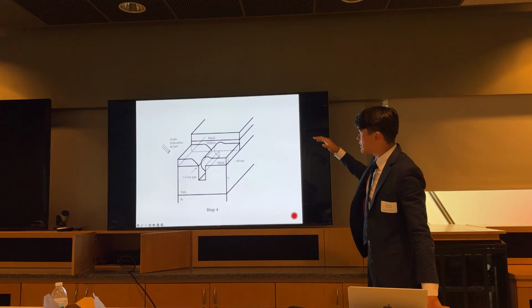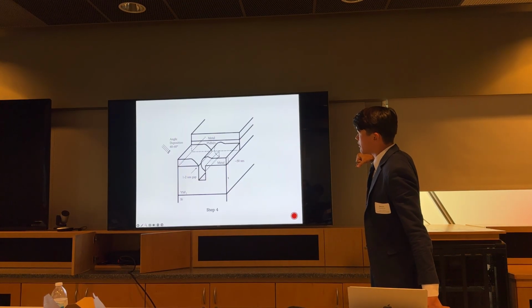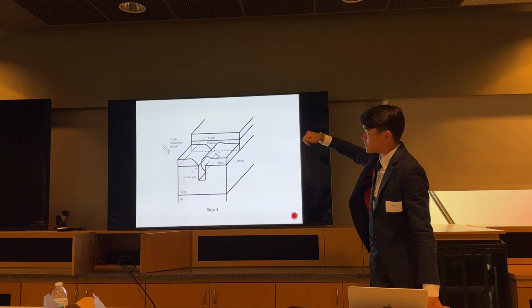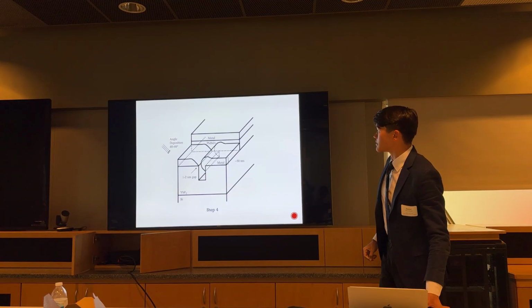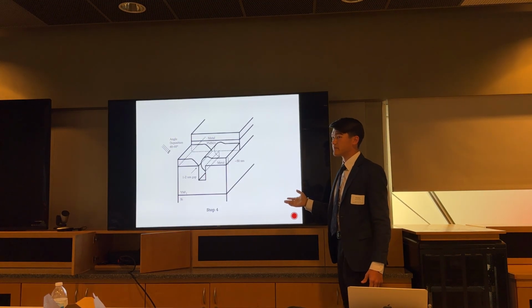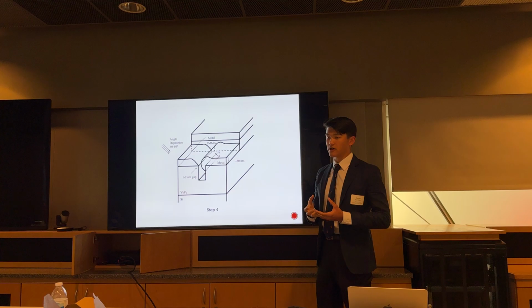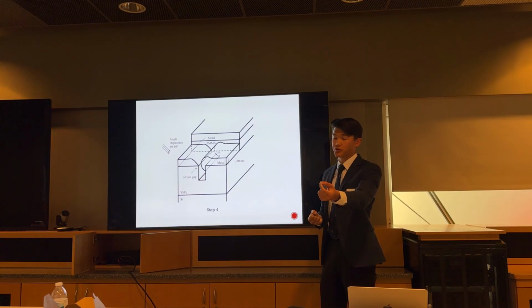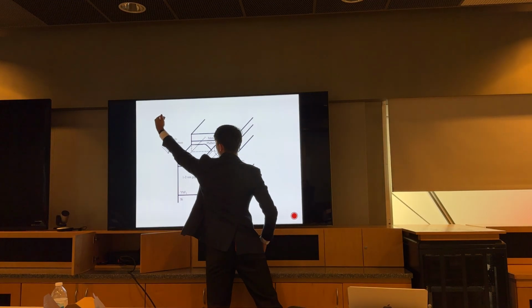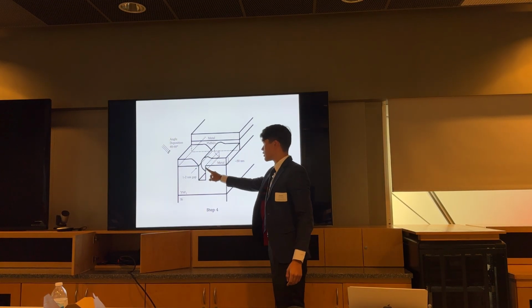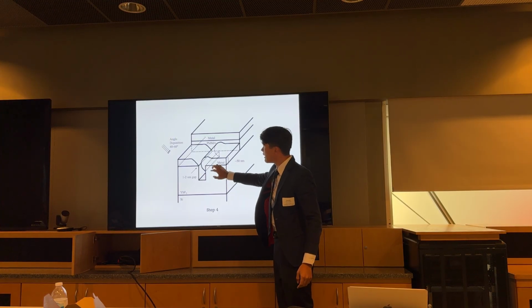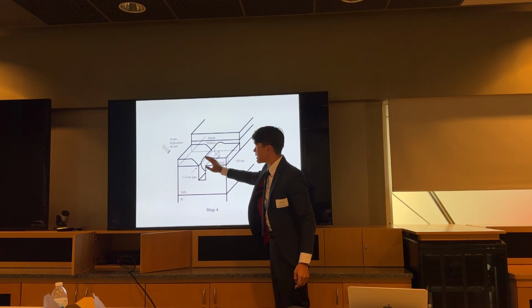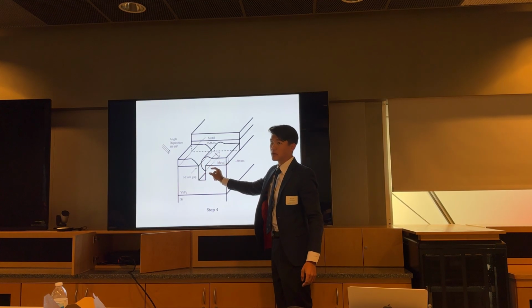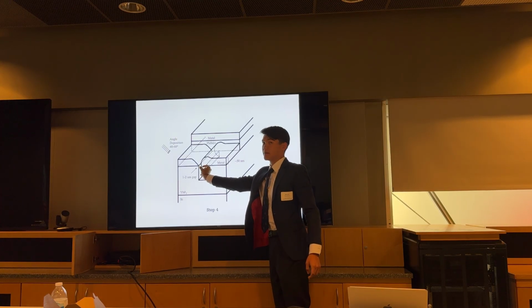With the PMMA orthogonal trench there, we can then deposit metal at an angle on the top. So this is also via physical vapor deposition, which means that the metal itself gets evaporated in a vacuum chamber. And because it's a vacuum chamber and they have the kinetic energy, they essentially just travel in a straight line. So they come in a straight line from this direction and begin growing from this corner of the trench. And so they naturally grow in this shape, and by stopping the deposition at just the right time, we can ensure a 1 to 2 nanometer gap here.